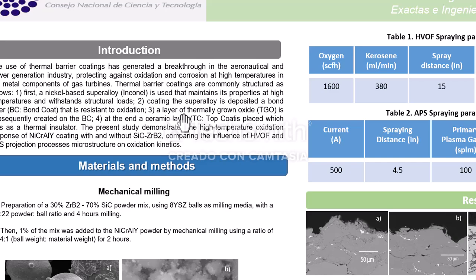Thermal barrier coatings normally fail when a determined oxide reaches a critical thickness. With this in mind, this work studies the oxidation resistance of commercial NiCrAlY coatings and coatings with SiC-ZrB2, projected with both HVOF and APS projection systems, comparing and analyzing which had a better response to oxidation.